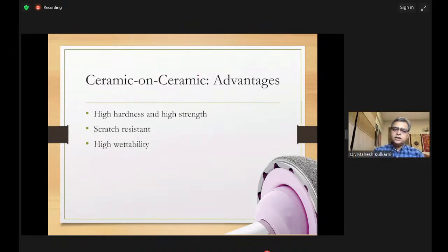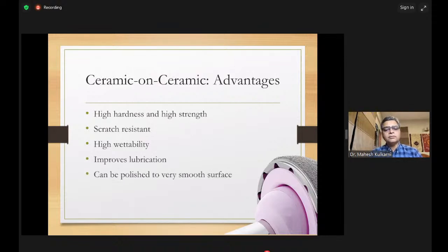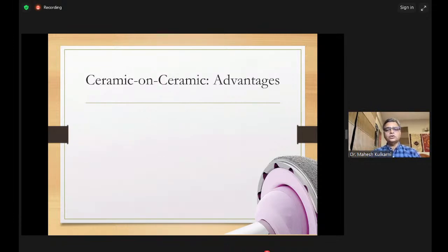and it won't spread on it. So the advantage is, if you understand tribology, if you have a hydrophilic material, it pulls fluid inside the joint and you get fluid film lubrication, which will reduce your wear rate. So that is the importance. High wettability, scratch resistance is much better as compared to stainless steel or even cobalt chrome or even oxidized. It improves lubrication, as I've mentioned to you, and the newer generation of ceramics can be polished to a very, very smooth surface.